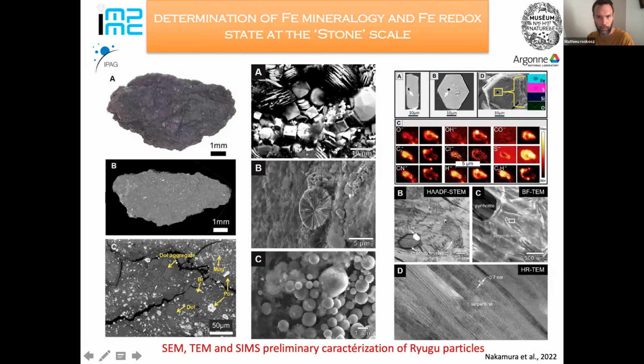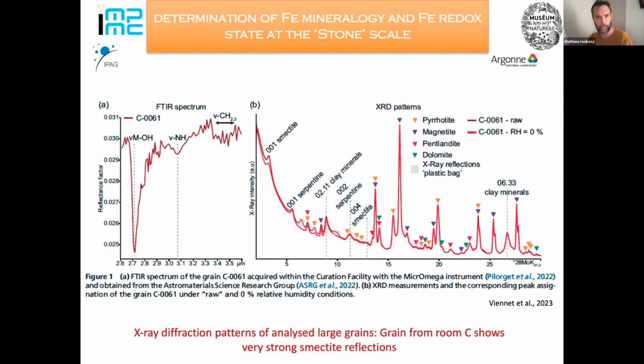And the last important class of minerals is clay minerals. So there's a lot of serpentine, as you can see here, and there's also smectite. So this is the mineralogy, and we knew that pretty much at the same time as when we collected data for the redox state of the grains. We also collected X-ray diffraction patterns on the beamline thanks to the setup installed on sector 3. And this is a typical spectrum for grain C61. And as you can see, there is a clear signal of smectite, serpentine, but also magnetite, pyrrhotite, pentlandite, and a little bit of dolomite.